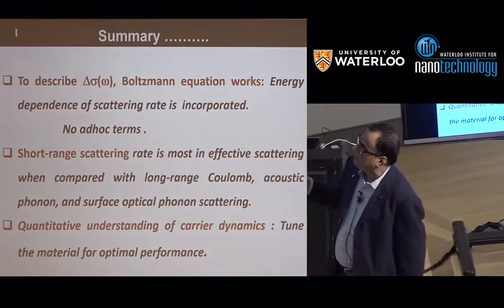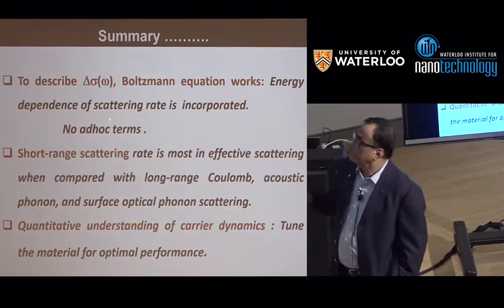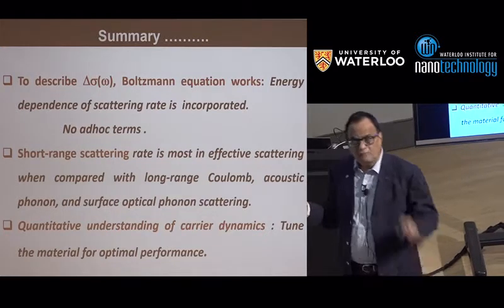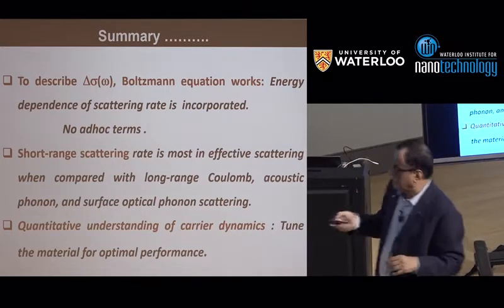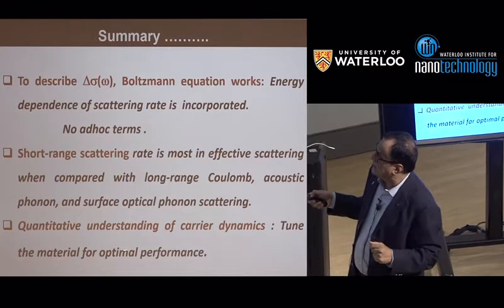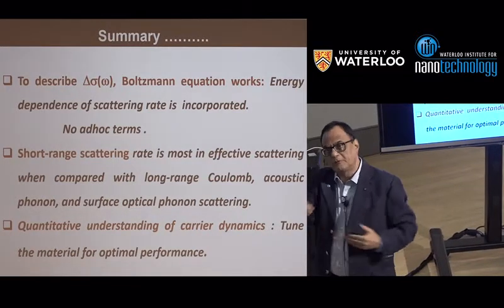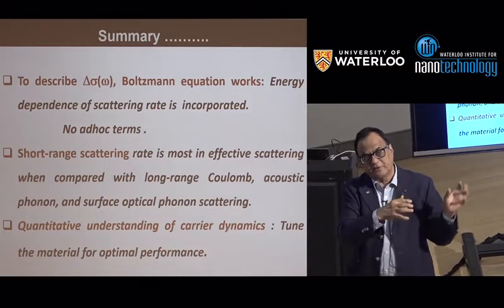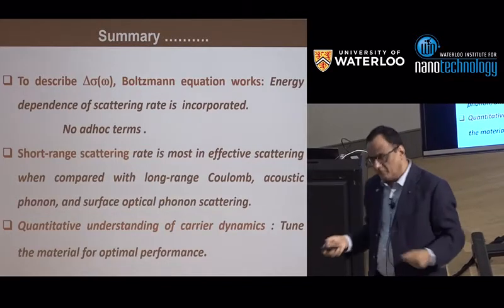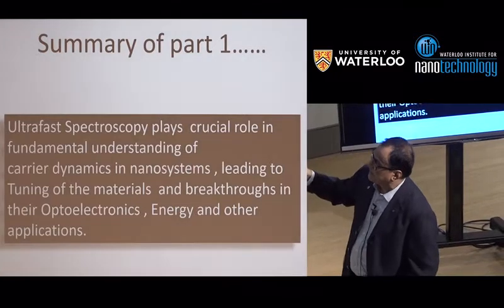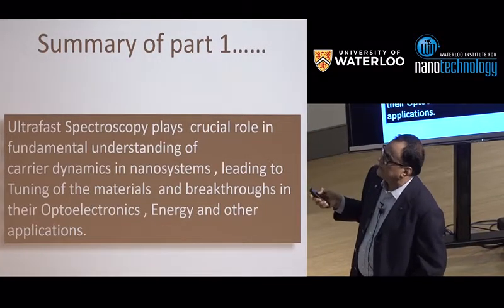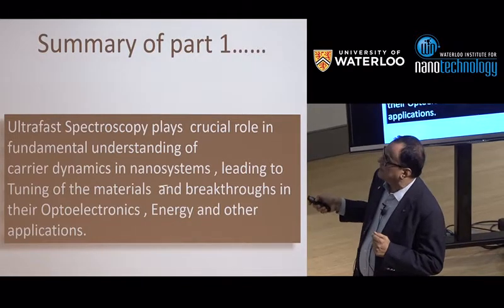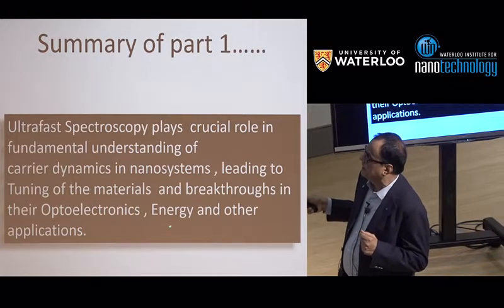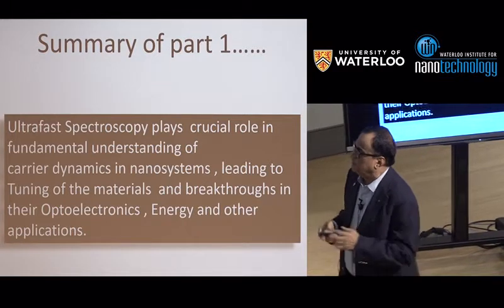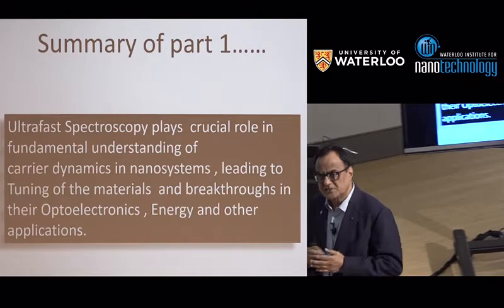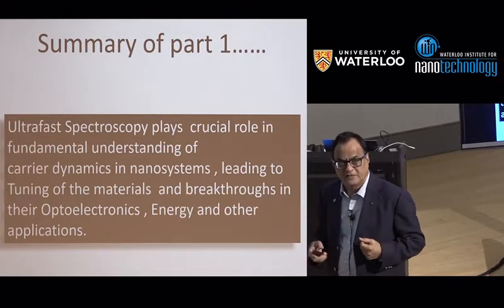But to summarize, now we have a quantitative understanding of photoconductivity, which gives you the idea what mechanism is contributing to scattering of photoexcited carriers, and gives you an estimate of how much disorder is there. Hopefully this quantitative understanding will tell us how to optimize the material, because now we can really see the connection between growth conditions and terahertz photoconductivity. This is the summary of the first part, which I have put as a take home message: this ultrafast spectroscopy gives you a quantitative understanding of carrier dynamics, leading to tuning of the material and how to optimize them for optoelectronics, energy and other applications, because most of the applications in photonics need these parameters and mechanisms.